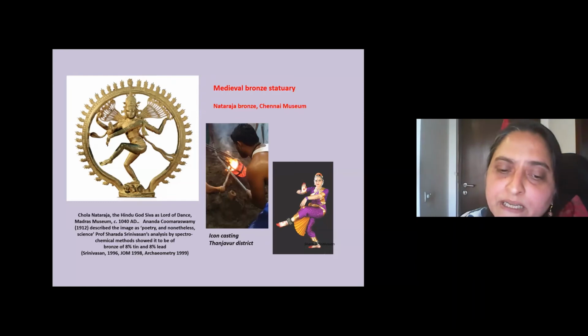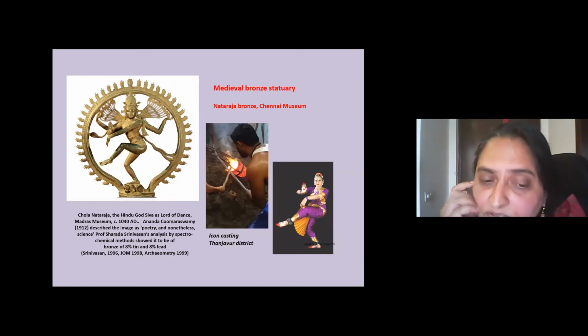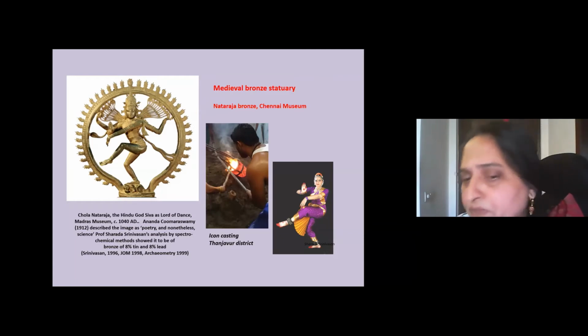And the analysis shows that it is a bronze of about 8% tin and 8% lead. So this is actually leaded bronze. A lot of these images were also of leaded bronze. And as you can see, there are still surviving traditions where the icon is being cast in the Tanjavur district.